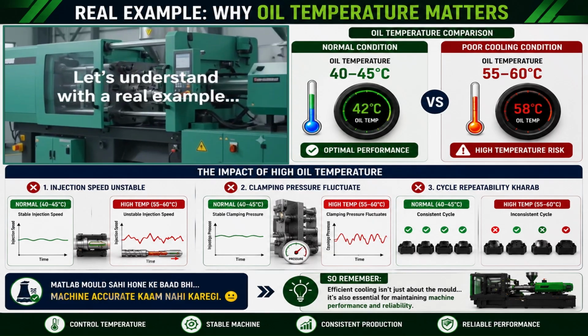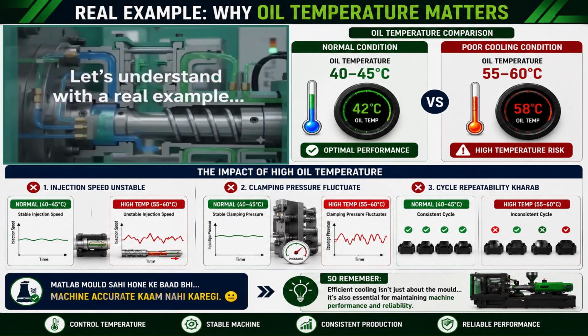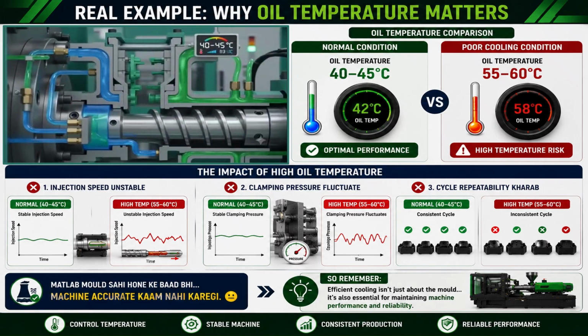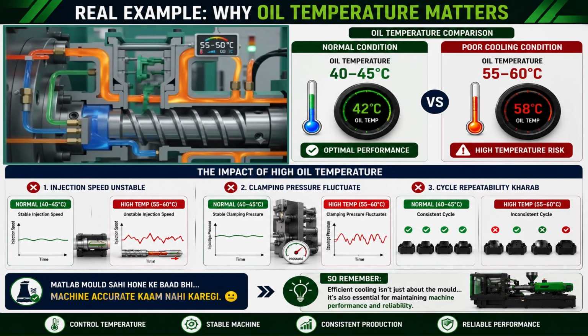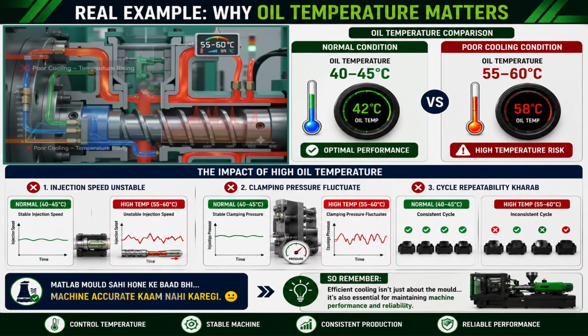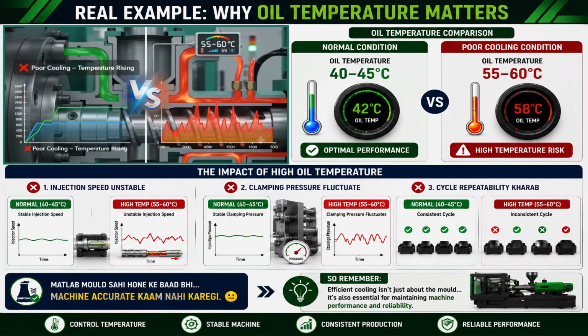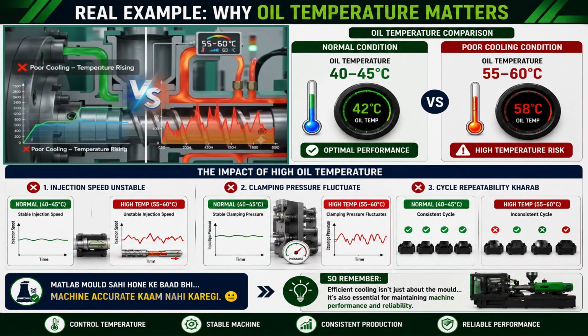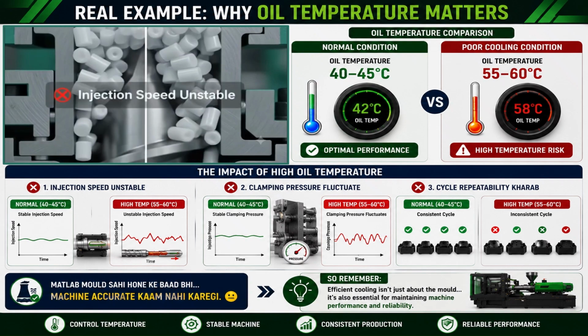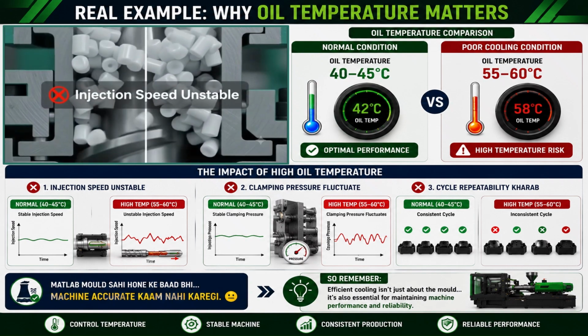Let's understand this with a real practical example. Under normal conditions, hydraulic oil temperature stays around 40 to 45 degrees Celsius. But with poor cooling, it can rise to 55 to 60 degrees Celsius. Now look at the impact this creates. Injection speed becomes unstable, clamping pressure starts fluctuating, cycle repeatability gets disturbed.